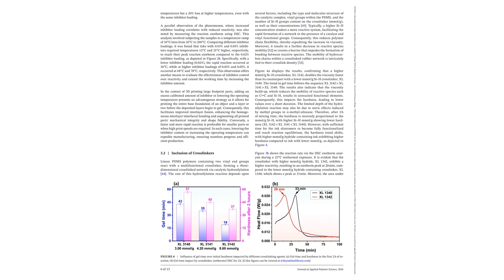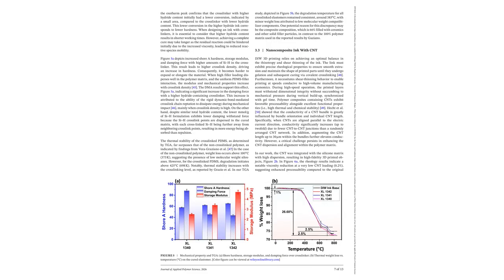The DSC analysis supports this, showing that the high hydride crosslinker initially has a lower degree of conversion, as indicated by a smaller exotherm peak area during an isothermal test. But given enough time to reach full cure and reaction equilibrium, this trend reverses. The higher hydride content ultimately creates a denser crosslink network. This leads to a material with higher Shore A hardness, a higher storage modulus, a measure of stiffness, and a greater damping force, which is the ability to dissipate energy from mechanical impacts. This demonstrates that by choosing the right crosslinker, engineers can tune the final mechanical performance of the printed part to meet specific demands.